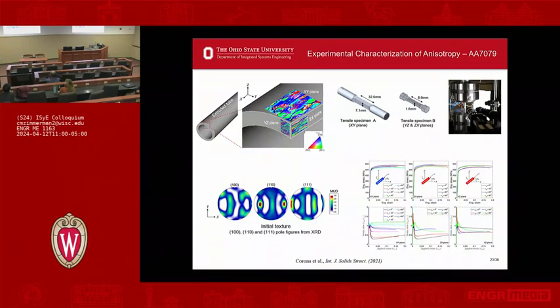They measured these. These are basically those textures that I was talking about, highly anisotropic. What they found out from these tensile tests is that none of these curves fall on top of each other, which basically means that this thing is highly anisotropic, not isotropic. And they also measured some other factors called R factors that, again, show they don't fall on top of each other. That means highly anisotropic.